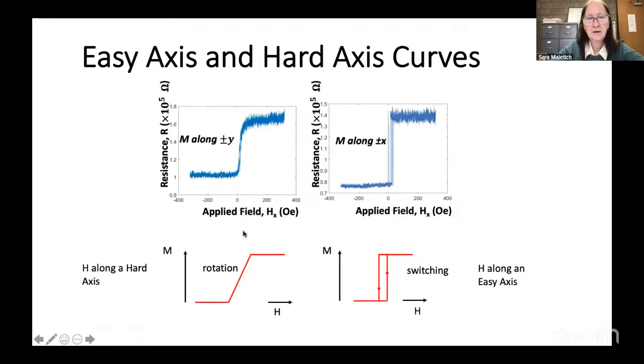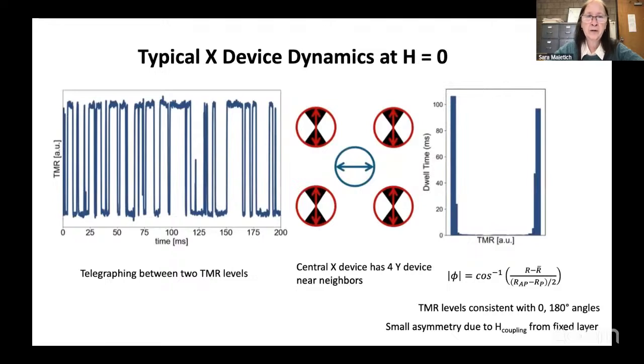If we have these other devices, they have more curvature. And what is happening is, as you apply a field in the X direction to a device that wants to be magnetized along Y, you're rotating that moment away from Y until you saturate and it really is along X or minus X. And you get this gradual rotation. So very different behavior, even though to first order the curves look similar. We can go farther with magnetoresistance because with these two layers, there's a relation between the relative angle of the fixed and free layer moments and the measured resistance.